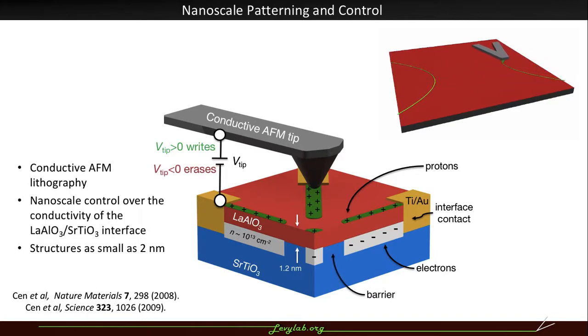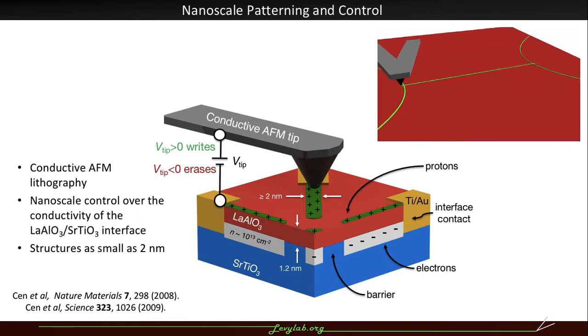Using this technique we can create structures as small as 2 nanometers and by applying a negative voltage to the tip we can even locally erase and create tunnel barriers in these devices.